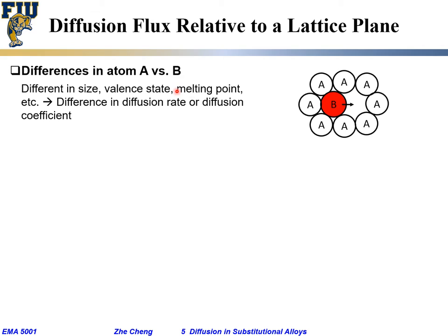There may also be a difference in melting point. Copper has a higher melting point than zinc. Zinc typically melts at 400 degrees C, copper at 1000 degrees C. Because of this, naturally, you would think there must be some difference in the so-called diffusion rate, or diffusion coefficient. Make sense? It's just that they are different.